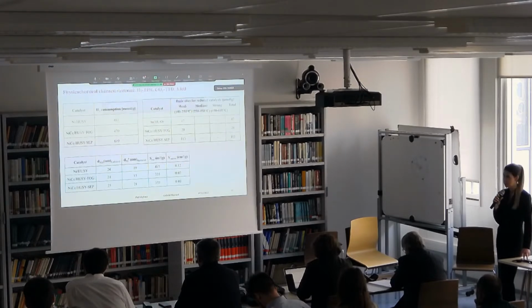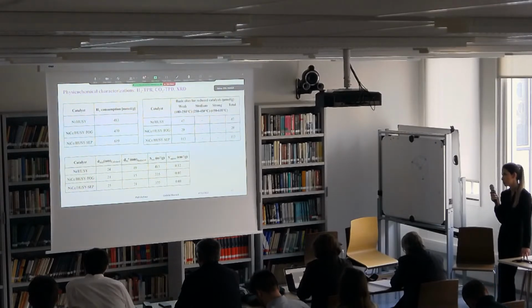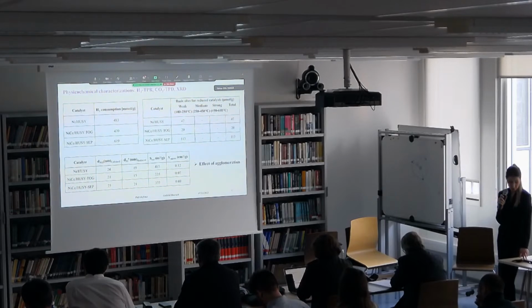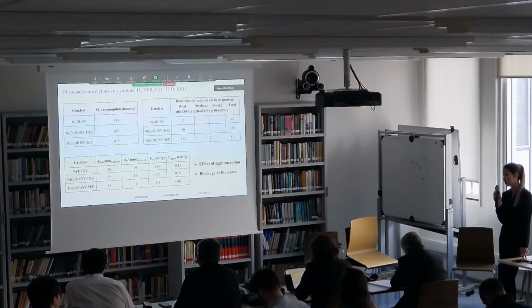mixed separately. Based on their physicochemical properties, in general, the addition of ceria improved the physicochemical properties of the catalyst, while for the separated samples the nickel particle size increased, which shows the effect of agglomeration. Also, with the addition of ceria the external surface area decreased, showing that with the addition of the second metal oxide, the entries of the pores of the zeolites are blocked, so the external surface area decreased.